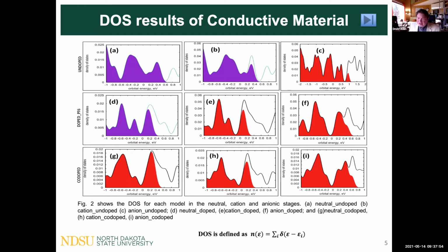Yes, okay, thank you. Professor Hung, does it satisfy your question, or do you need more explanations? I think that's fine. The main point here is it seems to have a small band gap. But during the calculation, there are broadening effects. You have to use either a Fermi function or a delta function with a finite width, right? And if the parameter is quite large, you get overlap. Exactly. And it's just an artifact from the calculation. Exactly, and it makes a deceptive impression on the graph. But objectively, the gap is here.